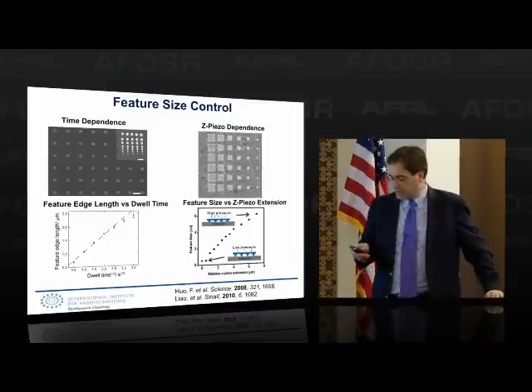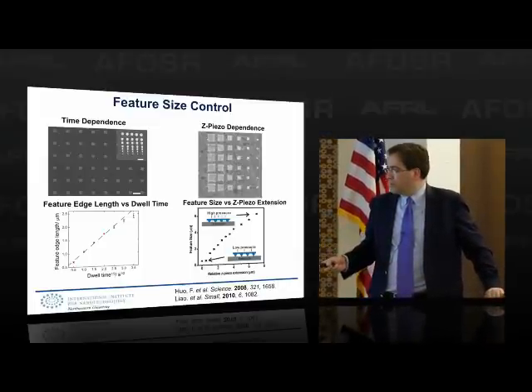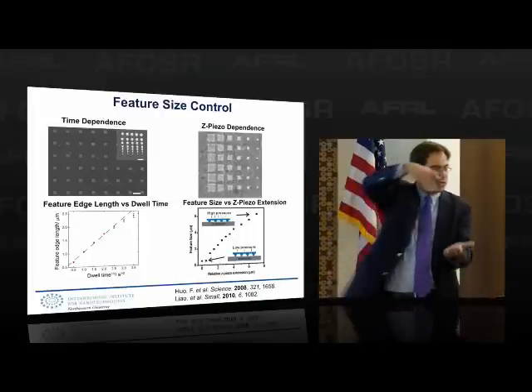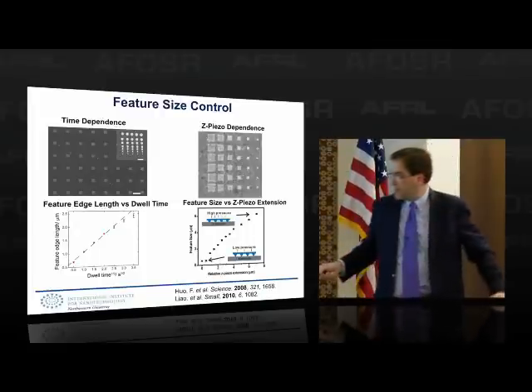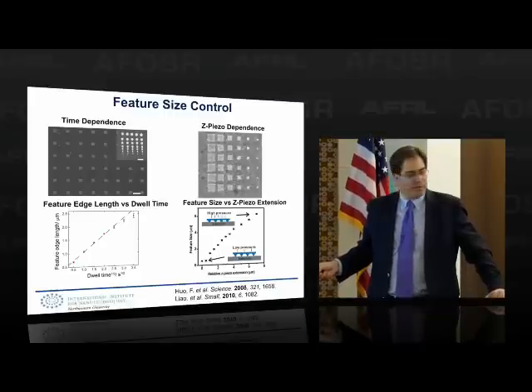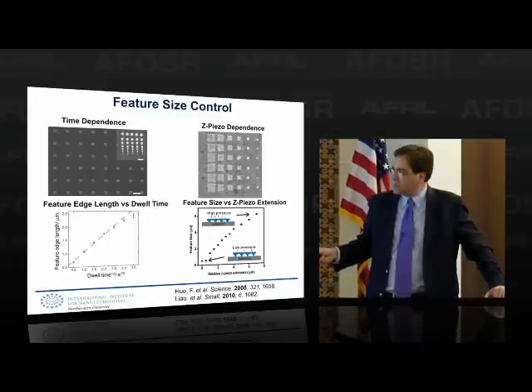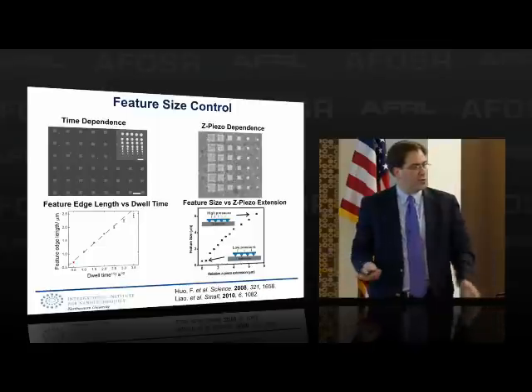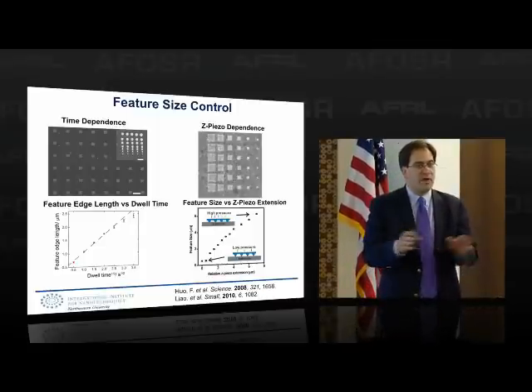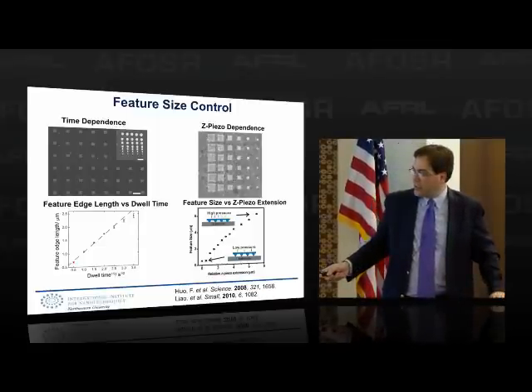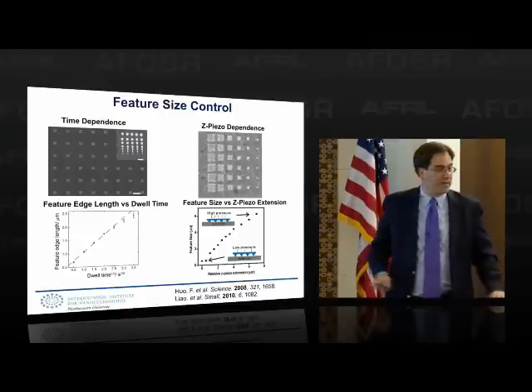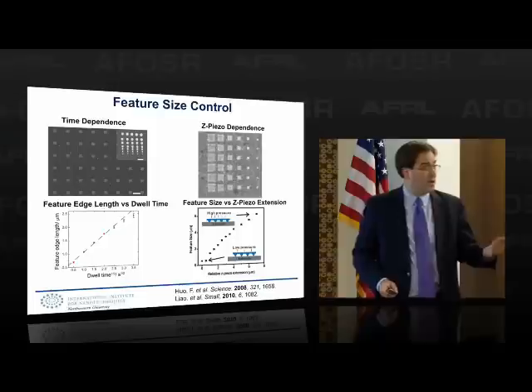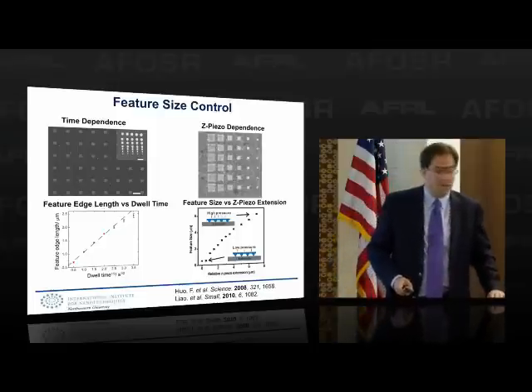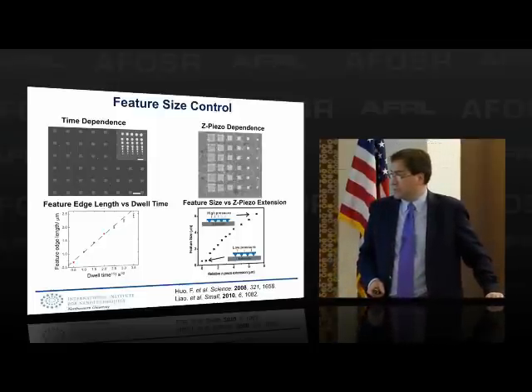And this is the observation. If you look at this, what you see is that the feature size is a function of relative Z piezo extension. So that's how hard we're pushing in the Z direction. Initially, it's incredibly forgiving. What happens is the base of the array absorbs most of the contact force before any of the tips are deformed. Then you get to a point where now the tips begin to uniformly deform. And in fact, I'm going to show you that's very modelable. We can literally model that and automate this to create a very, very sophisticated system.